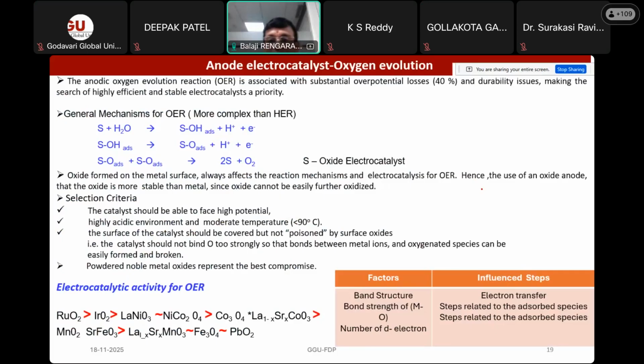As I said, though the theoretical voltage is close to 1.4 volt to split the water molecule into hydrogen and oxygen, in the practical case it will require 2 volt DC voltage to split the water molecule into hydrogen and oxygen. Most of the energy in this case is being used for the oxygen evolution, not for the hydrogen evolution, because the reaction kinetics for the hydrogen evolution is faster than the oxygen evolution.